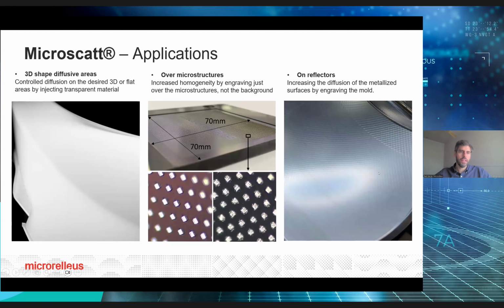Some applications of the texture in the market: 3D shape diffusive areas over microstructures. For example, if we engrave some microprisms for a surface light guide, a light curtain, and in addition to the microprism, we engrave the Microscatt over the prism, we are going to avoid the hot spots, the torches of the light, getting a better homogeneity without losing too much light. Or on reflectors, if you want to increase the diffusion of the metallized surfaces.